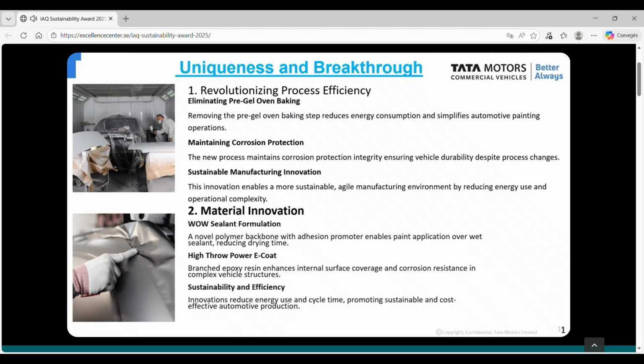We developed a wet-on-wet sealant formulation featuring a novel polymer backbone and adhesion promoter. This allows paint to be applied directly over wet sealant, eliminating the drying step and reducing cycle time. We also introduced a high-throw E-coat using a branched epoxy structure. This enhances internal surface coverage and corrosion resistance, especially in complex vehicle geometries.